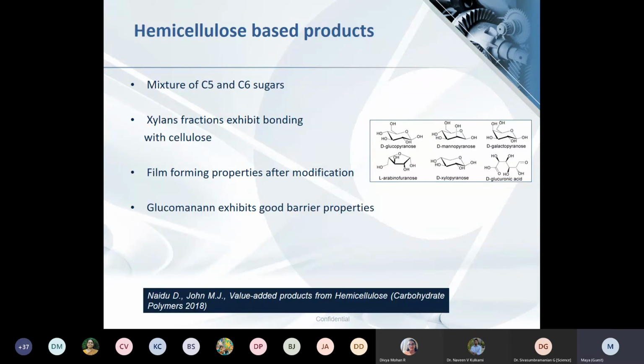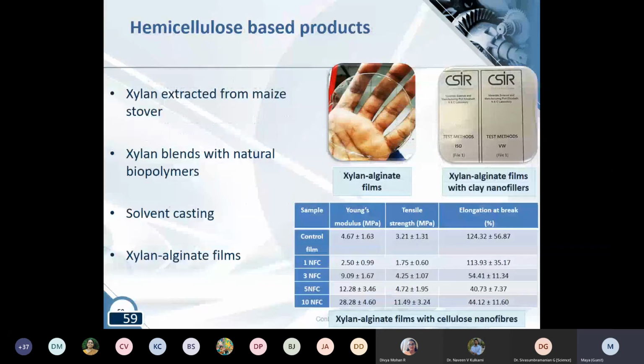This is again my work of my PhD student. So this is about hemicellulose-based products. Hemicellulose, as I said earlier, is a mixture of C5 and C6 sugars, and one of the most important fractions is xylans. Xylan has good barrier properties, and it can also form films, usually when you are blending it in another biopolymer. So my student's work entailed extracting the xylan from the maize stover and then blending it with natural biopolymers.